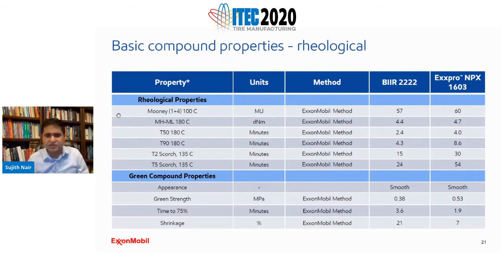The MH minus ML is slightly higher for Exxpro. The T90 for Exxpro in this particular curing system is twice that of bromobutyl. But as I said, there are multiple different ways to equalize the T90s. One of the common ways that we tell people is to add a little bit of Voltac, and you can basically speed up your T90 to a great extent.